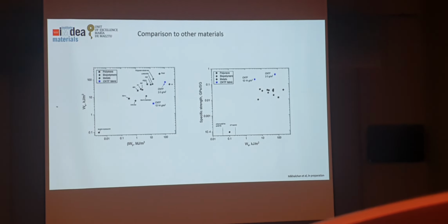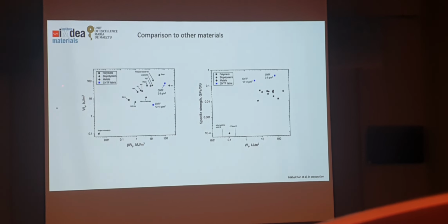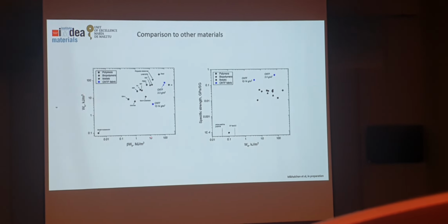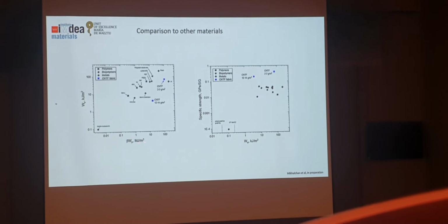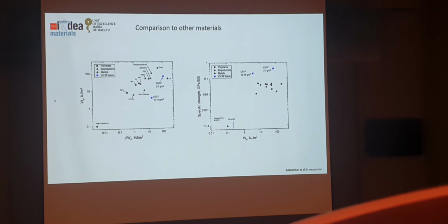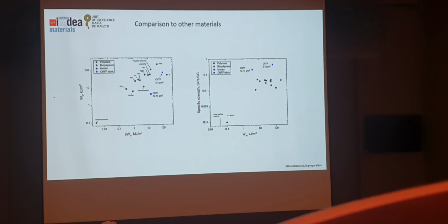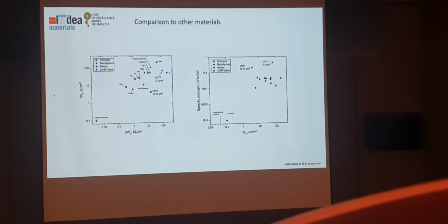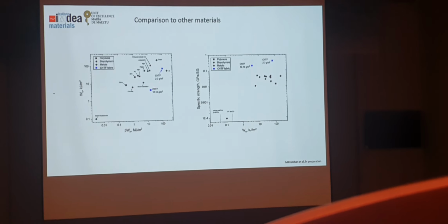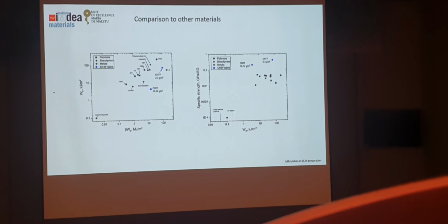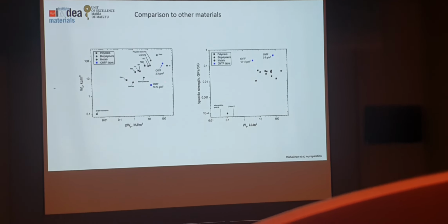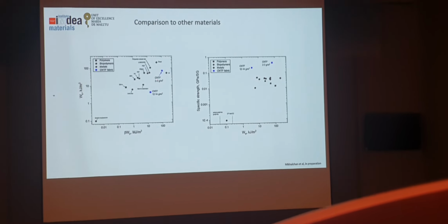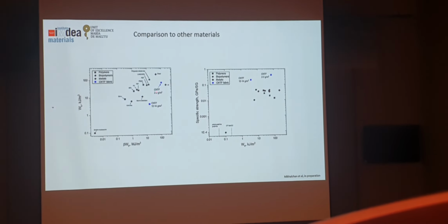So how do CNT sheets compare to other materials? This is a plot of the essential work of fracture, and then the plastic, more geometry-dependent parameter. As you can see on this scale, this is for the commercial and this is for the one produced at Vilatela. Both have a very high essential work of fracture, so that's good. It doesn't seem like we sacrifice fracture toughness by aligning.